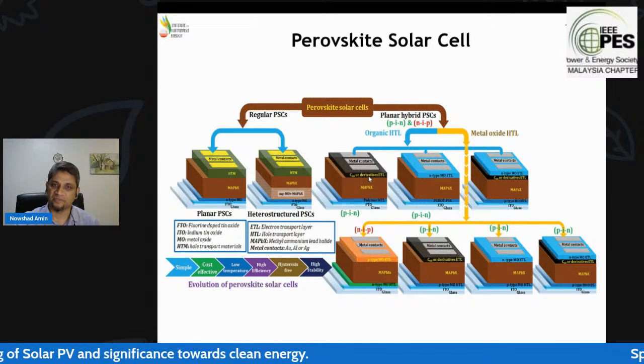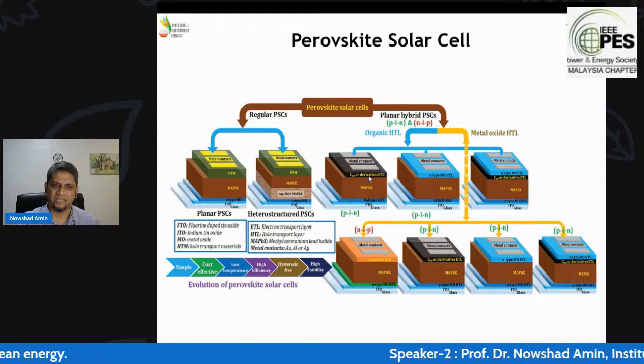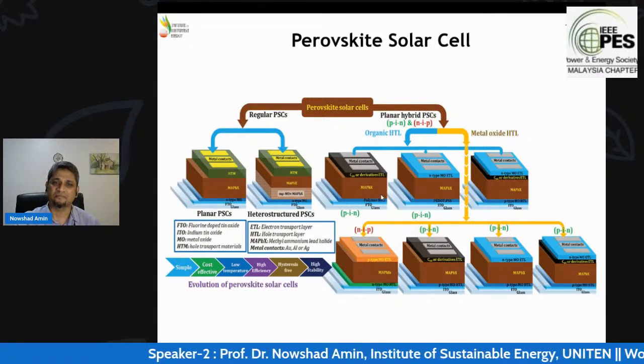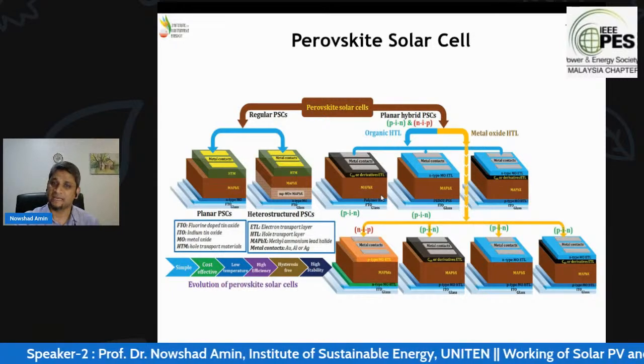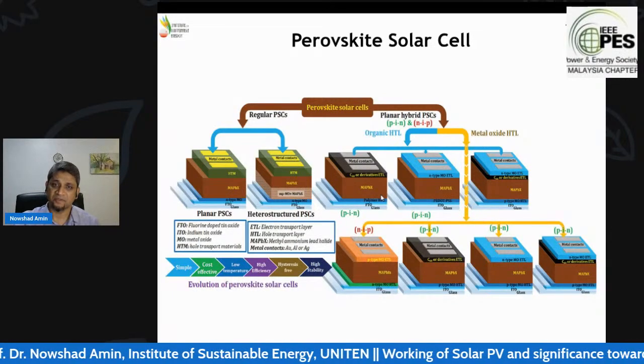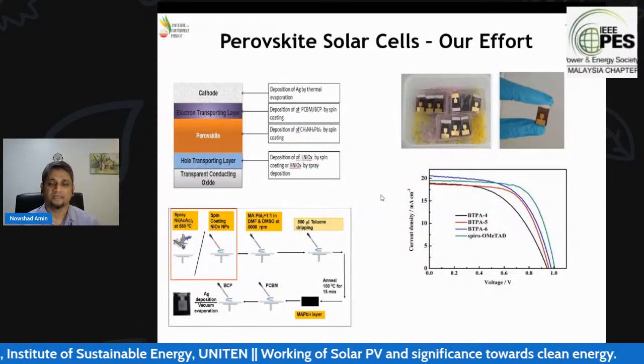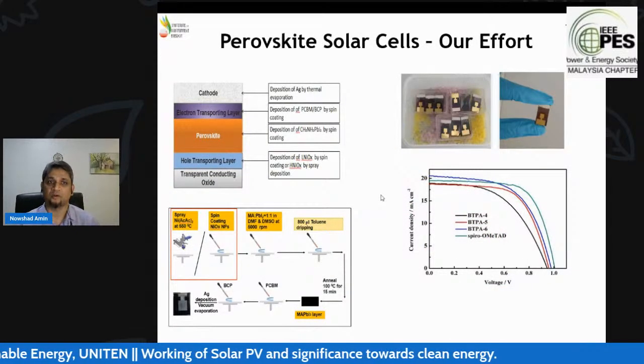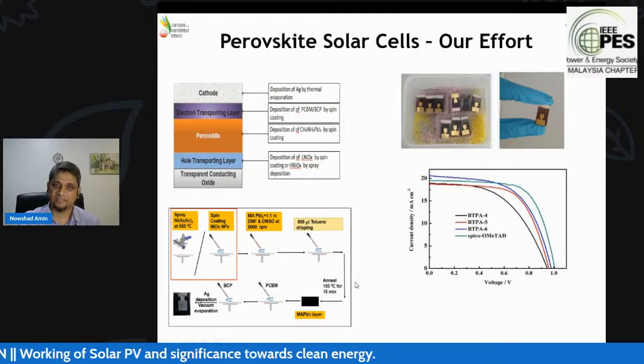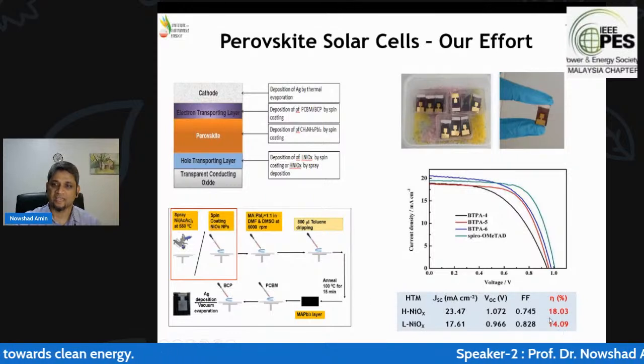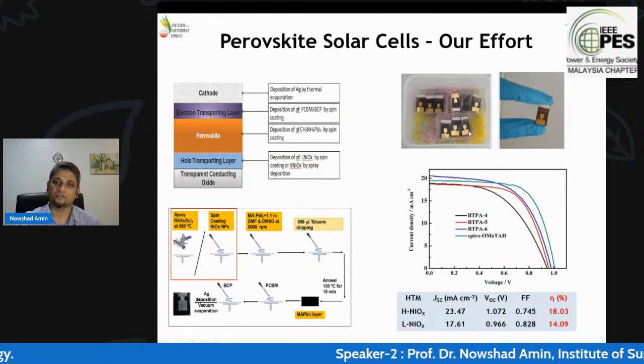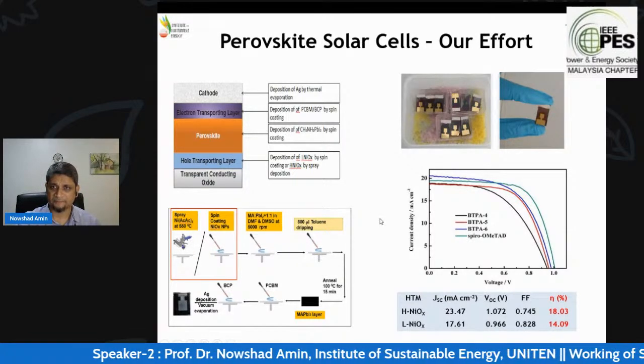So we try to make it in different ways, superstrate and substrate configurations, and different materials, different HTM, hole transport material, electron transport material, even perovskite itself. We try to make it methylammonium lead iodide, methylammonium lead halide. I mean, there are different options we can do. So still, there is some room to go for us as well. In our research facility, together with Japanese collaborators, we have made solar cells which are almost 18% efficient using a nickel oxide HTL, hole transport layer.